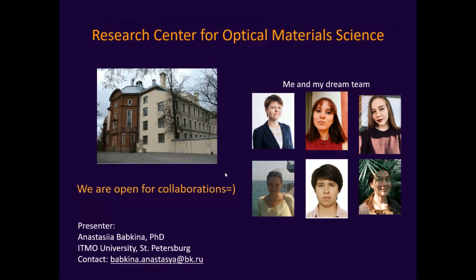Thank you for your question. It's a very good question. And yeah, the size is our problem, because when we have such big shifts, it means that we are working in the regime of the quantum size effect, and it means that our nanocrystals are smaller than the exciton Bohr radius. For bromide crystals, the exciton Bohr radius is 7 nanometers. For iodide, it's 12 nanometers. So in both cases, our nanocrystals are smaller than this number.